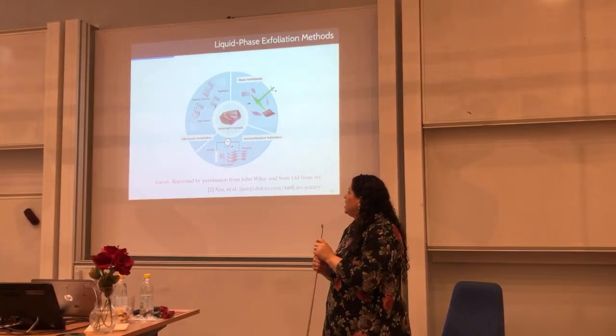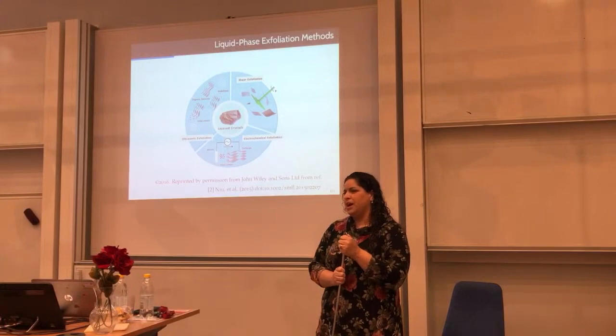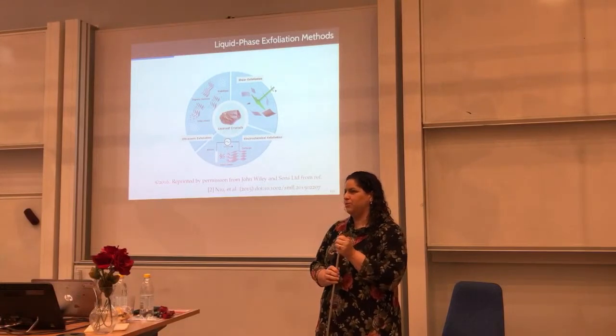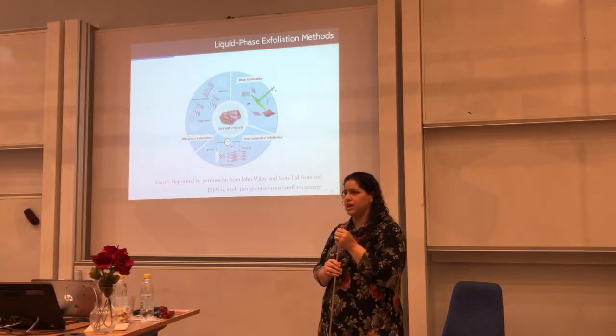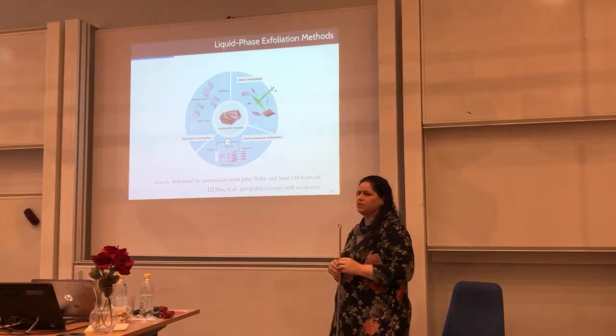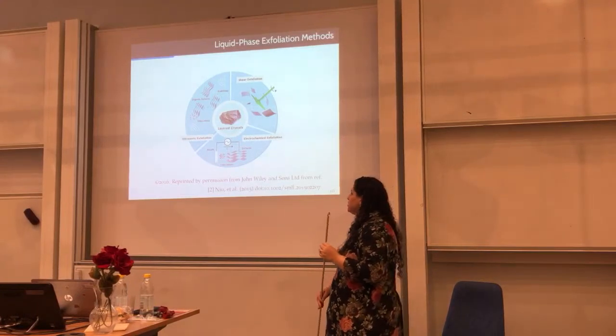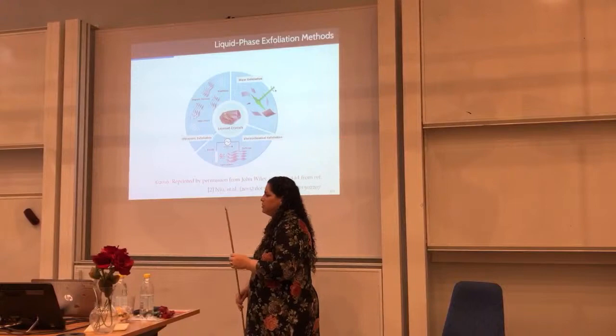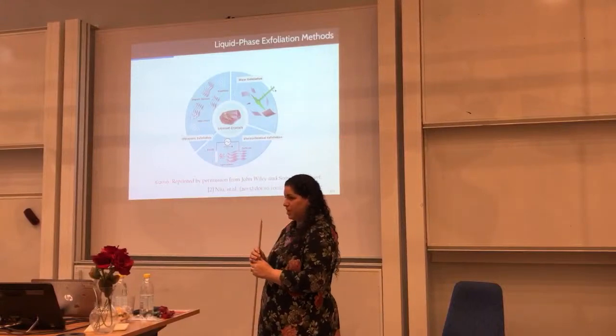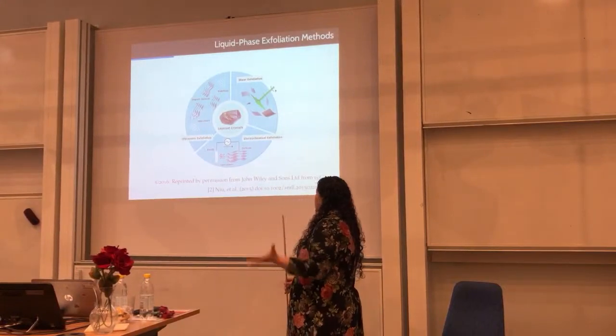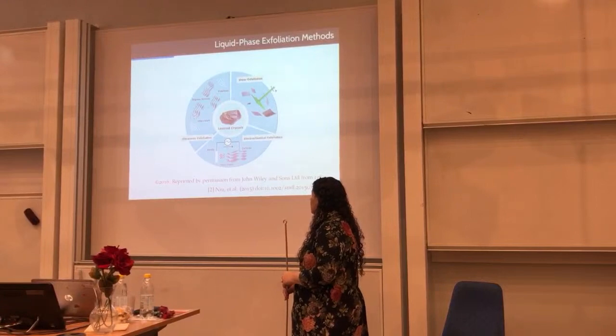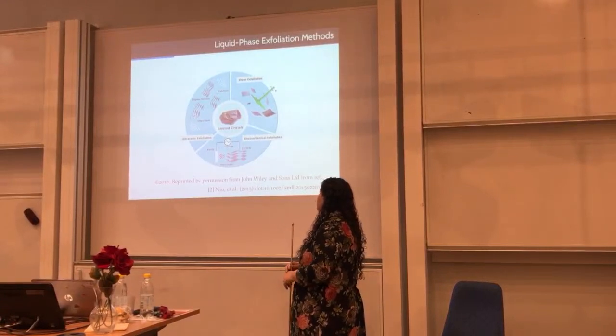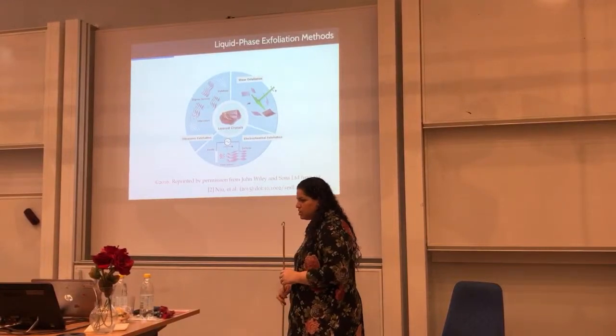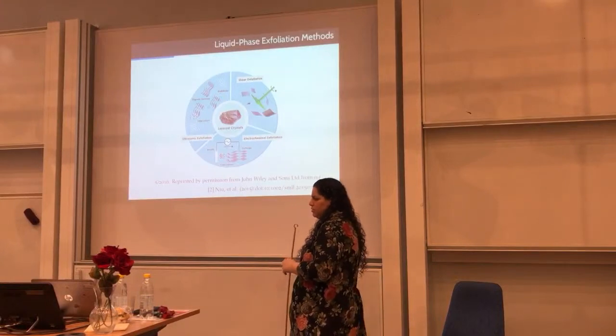But at the price of being highly toxic for the environment and for a pregnant woman, for an unborn child. So we need to avoid those solvents at all costs. That's why this thesis is interesting, because we're focused on this replacement. Besides the ultrasonic energy, what you can do is shear exfoliation. Shear exfoliation has the advantage of